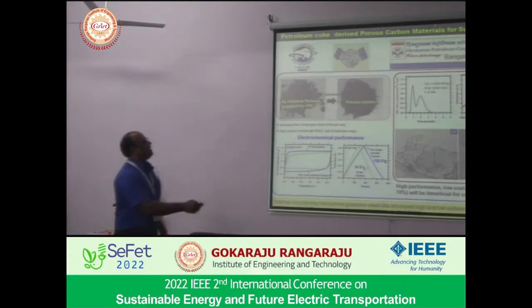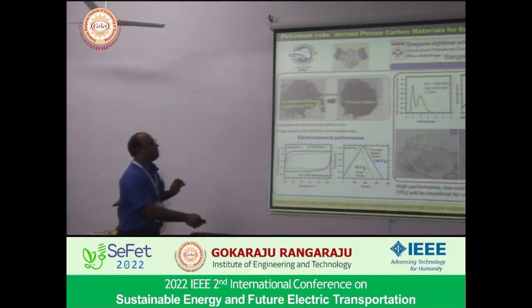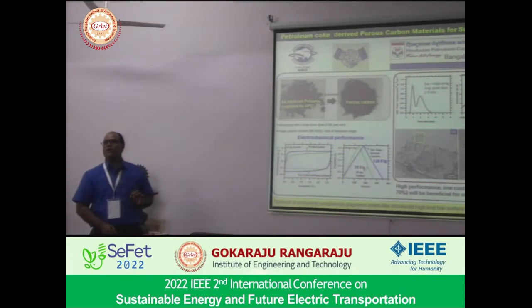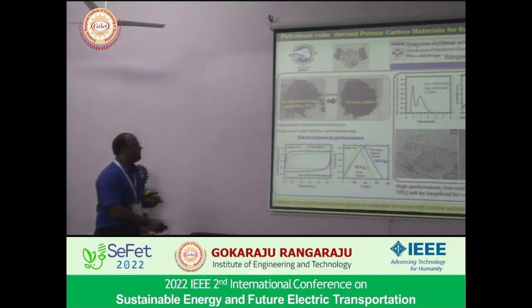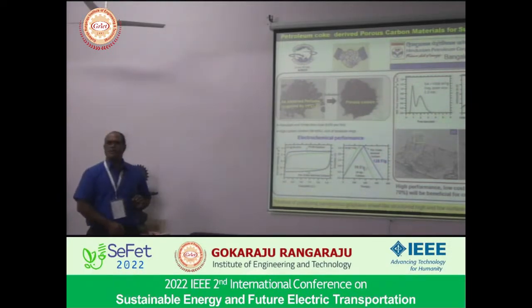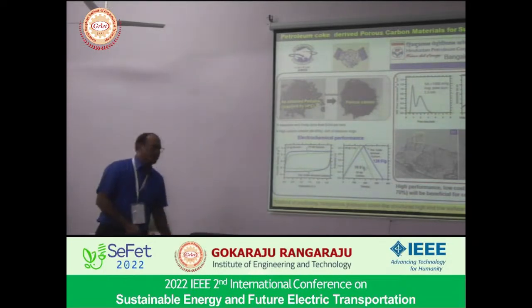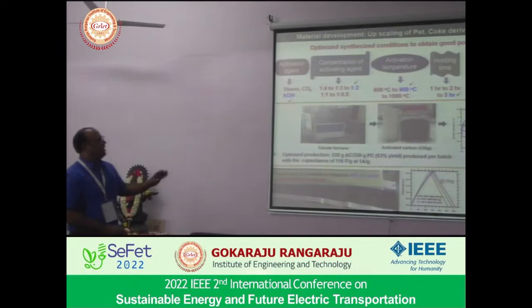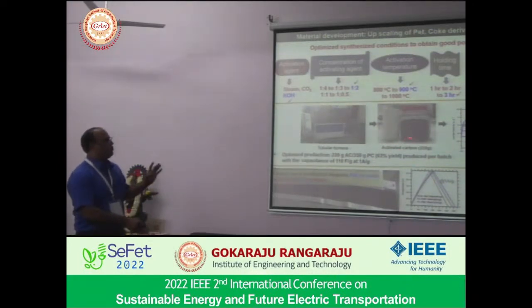If you look at all the characterization properties, the surface area is about 1500 meter square per gram. Here also we are getting few-layer graphene-like structured carbon in the petcoke derived carbon as well. And when you see the performance, the performance of our petcoke derived carbon is 128 farad per gram, compared to the commercial one, which delivers only 98 farad per gram. With this we have developed the material, and we have scaled up to 220 gram per batch, and that material also delivers 116 farad per gram.